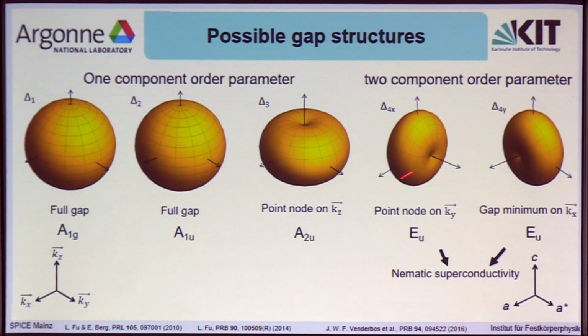So delta 4x actually has a point node that is along the ky direction, which corresponds to our A star crystallographic direction. And it's a point node that is symmetry protected, as I have told you before, that this is a symmetry axis in our system. In the case of the delta 4y, we actually have a gap minimum along the kx direction, which is a minimum because it's not symmetry protected, as it's along the a-axis, which is not a symmetry axis in our system. So those two would actually explain the nematic superconductivity that we are seeing in our system. So how can we tell which one of the two is realized in our system? And I will show you two experiments regarding this.